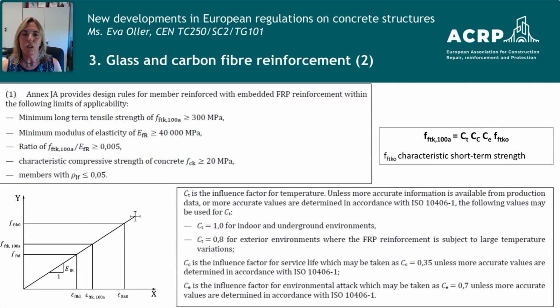So for design, we should consider the long-term strength that can be obtained from the short-term strength by applying some parameters that depend on the temperature, on time, and also on the environmental conditions. And instead of applying this type of parameters suggested by the Eurocode, we can also perform long-term tests in order to have the long-term strength that is going to be used for the design with this type of reinforcement. And this type of reinforcement is only recommended for tensile reinforcement, not for compression.